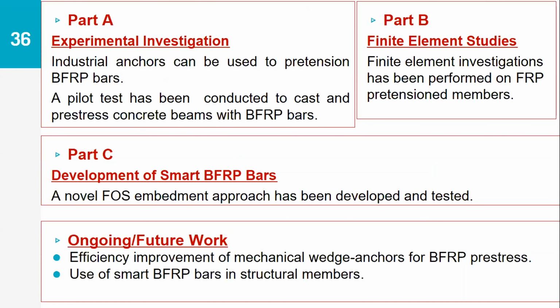So this is the overall summary. First is the experimental investigation that was conducted on the industrial anchors to pretension BFRP bars, as well as the pilot test that has been conducted to cast the prestressed concrete beams with BFRP bars. And then a finite element investigation has been conducted on both the mechanical anchors as well as the test setup to study the transfer length and transfer stage parameters, which are important for developing design guidelines for these BFRP prestressed concrete beams. And finally, a smart BFRP bar has been also developed and tested, which can be used for practical implementation.